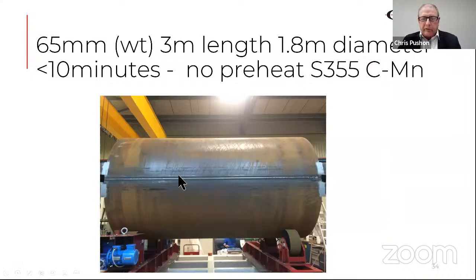And what we've since done is a 3 meter long monopile foundation demonstrator. In this case, it's 3 meters long. It's a pin pile for a jacket. It's in S355, a carbon-manganese steel. And the welding time is about 10 minutes. So again, this is with no wire, no flux, and no preheat. So apologies for people who sell welding consumables, but this might not be very attractive to them.